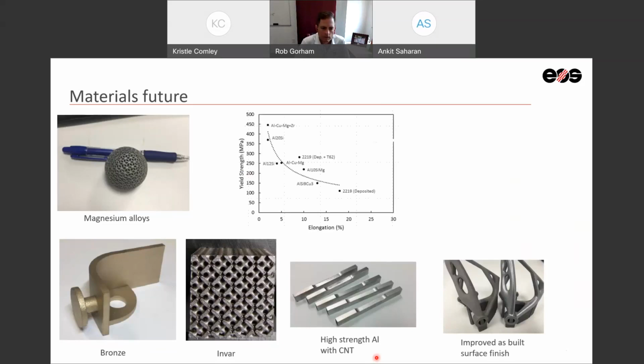And we're talking of new kinds of aluminum. Very quickly, here's where most of the additive aluminum alloys fall in the yield strength versus elongation ratio. Here's your silicon 10 mag, here's your silicon 10-3, here's your F357 silicon mag, and I don't see a 7-1, but I can see 7 silicon mag is somewhere here. What it actually shows is this space is quite empty, and that's where we see new aluminum alloys coming up. We're working on an internal aluminum alloy development that is going to put the alloy right here in this space, with a high strength of about 450 MPa and much higher elongation, about 15%. That is not entirely unheard of, but hopefully it helps customers drive aluminum adoption in the industry as well.